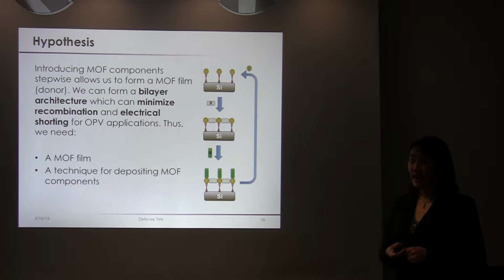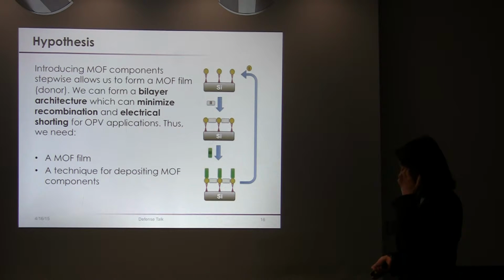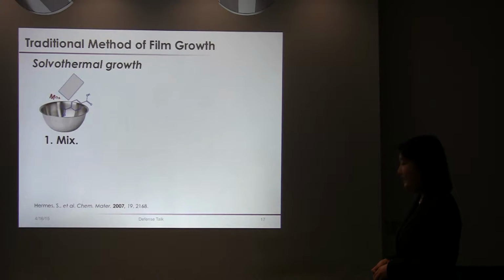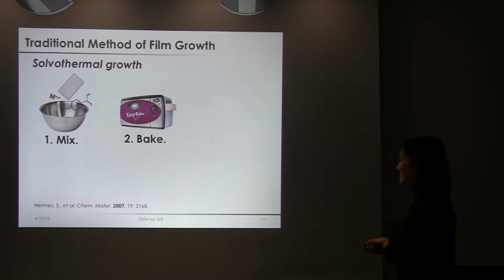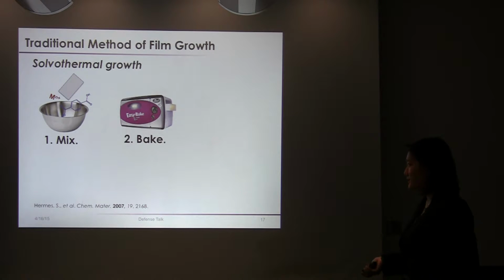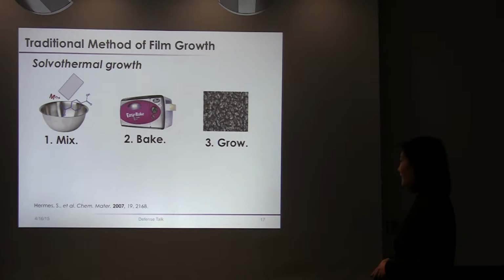So this essentially means I would need 2 things: 1, a MOF film, and 2, a technique for actually depositing these MOF components. So let me also introduce to you current techniques. The traditional method of actually forming films involves solvothermal growth. And this involves the mixing of inorganic precursors as well as organic linkers onto a pre-functionalized substrate in a high boiling solvent, and then baking this, or heating it at elevated temperatures for several days, and then forming a film of